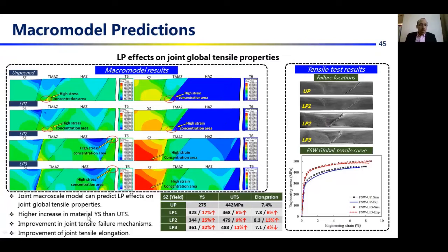For the joint global tensile properties, the macroscale model can predict the laser peening effect on joint global tensile properties, and as you can see in this curve, a higher increase is also observed in the material yield strength than UTS because of the work hardening effects that only affected the yield strength, and the improvement in the joint tensile failure mechanisms. As you can see, before laser peening, we have a higher stress concentration because of the heterogeneity of mechanical properties, which is avoided by the addition of laser peening layers. And this one from the experiments can be seen that the failure location relocates from this border to the central area, which increases both tensile strength and elongation.